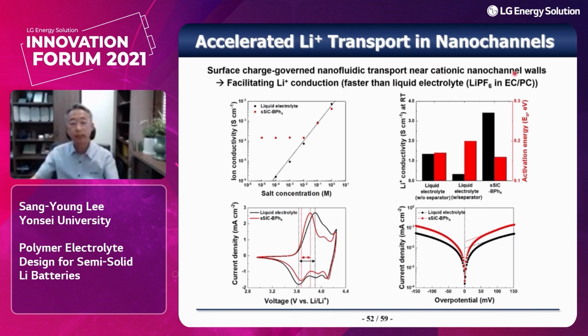Okay, and here we have measured the lithium cationic conductivity at room temperature compared to the liquid electrolyte, and the activation energy was lower than the control sample. And this is the evidence demonstrating the benefits of the electrolyte.